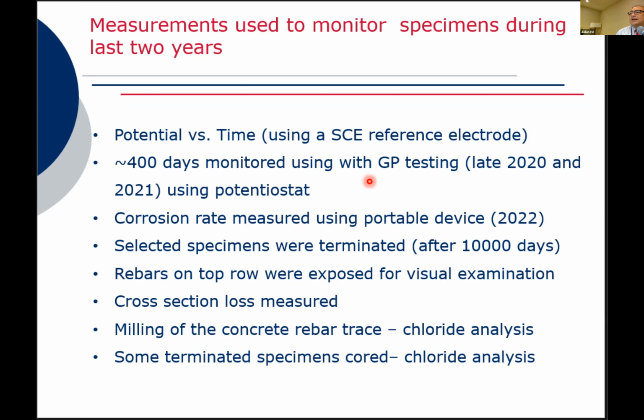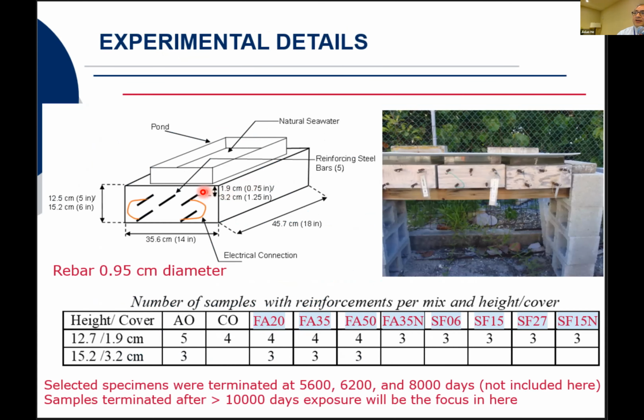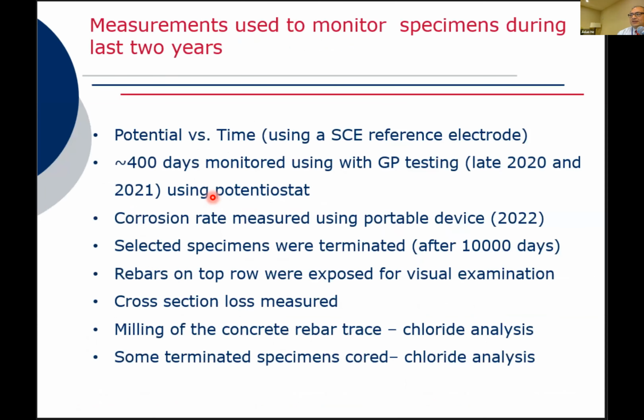Selected rebars were selected for forensic analysis, and in some cases, we only terminated one. From the diagram that I show you here, if we found that the crack was only above this rebar, then we did a longitudinal cut, and we only exposed the rebar that is on the right. We also did 2 additional transverse cuts without touching the rebar, and then we applied a chisel to open up and remove the top, so we can observe the surface condition. In some cases where we removed either 2 or 3 rebars, we also cored the specimens.